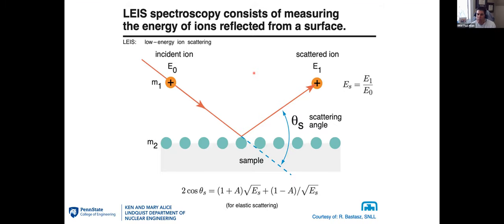So we utilize a number of different techniques. One technique is known as low energy ion scattering. I'll go over this technique as we go through some of the case studies, but just to give you a brief introduction, the idea is to use an incident energetic ion that comes in and interacts with the surface and then scatters at some scattering angle. And the technique is such that we are able to detect only those particles that scatter as ions. In scattering, 99% of the ions that come in are readily neutralized. So we're basically capturing only the less than 1% of ions that survive neutralization, which end up being the ions that are scattering with basically the top layer of the surface. So that's one technique we use.